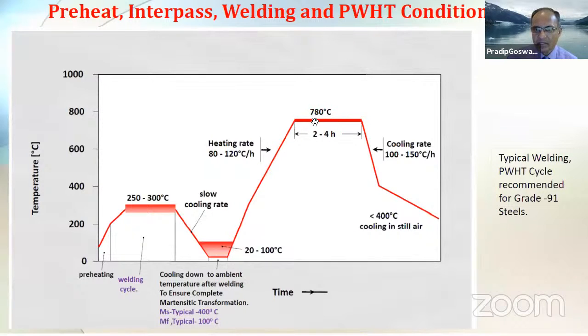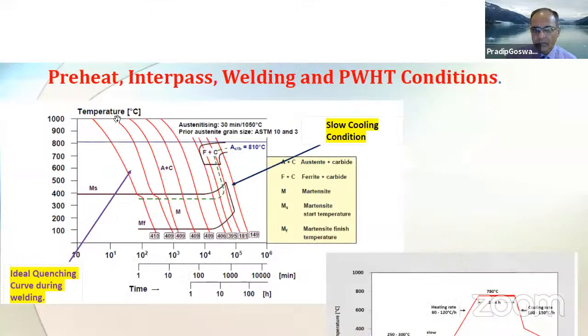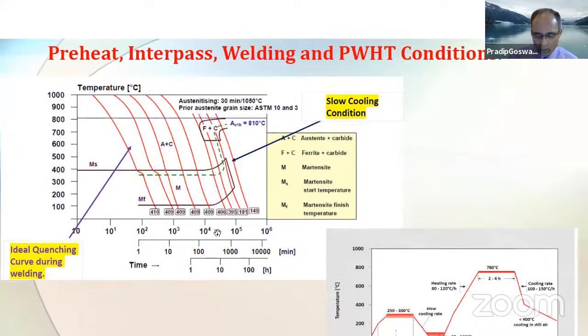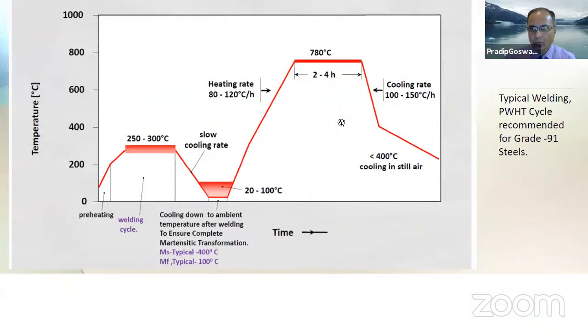That is typically nominally 780 degrees centigrade, or it could be below also, at a nominal heating rate of 80 to 100 or 80 to 120 degrees centigrade per hour. Following soaking of 2 to 4 hours, typically depending on the section thickness and the design code, it has to be slowly cooled to the room temperature.